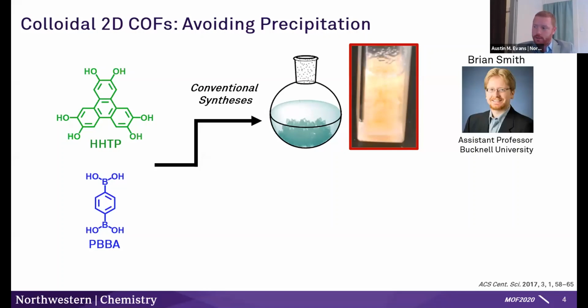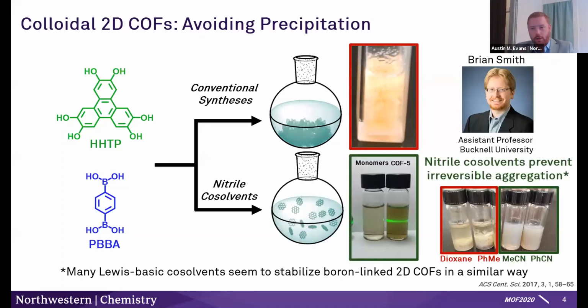So my colleague Brian Smith, who was a former postdoc in the Dichtel group, noticed, just as I was joining the group, that if you include nitrile co-solvents in the reaction of boronate ester 2D COFs, you actually avoid this precipitation event. And that is really enabling, because in earlier studies, we had found that this precipitation event largely limited the crystallite growth and the extension of the lattice. You can think about that as the heterogeneous problem. When crystallites start to aggregate, they're more challenging to grow.